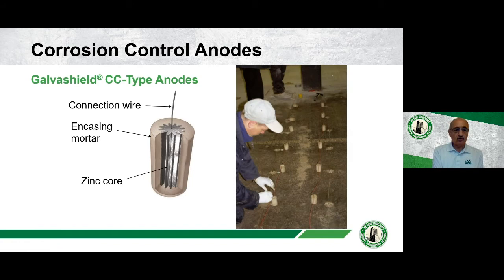Okay, I talked about the CC type anodes briefly. They're just the same chemistry. Basically, you have an encasing mortar with lithium hydroxide, and you have a zinc core, and these are put into drill holes on a concrete slab. Again, this is a parking garage, and you can actually connect all the anodes, or a lot of anodes, I think up to 20 anodes in a chain, once you've inserted them into the concrete.